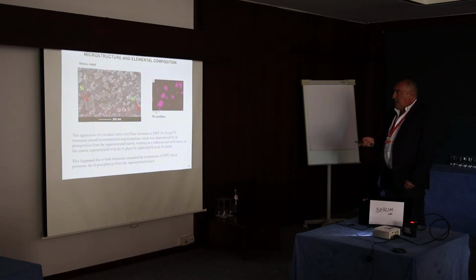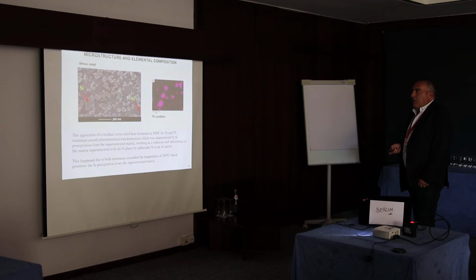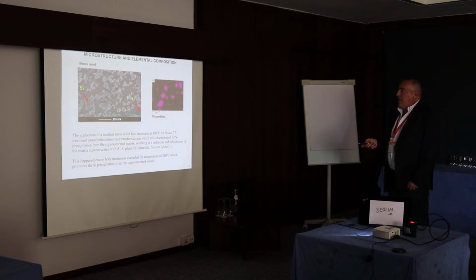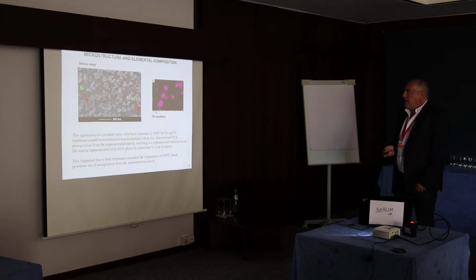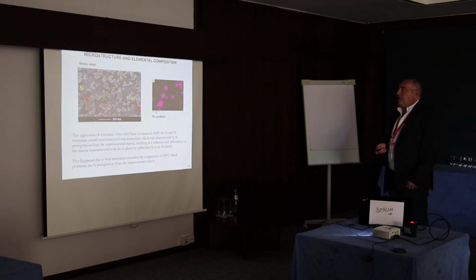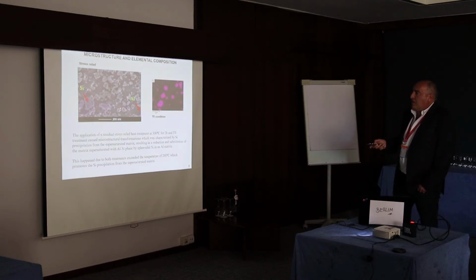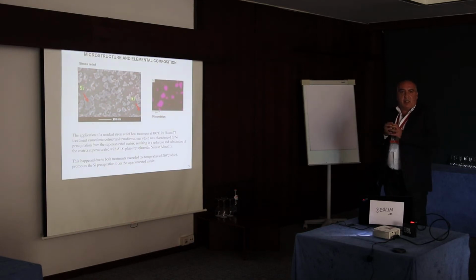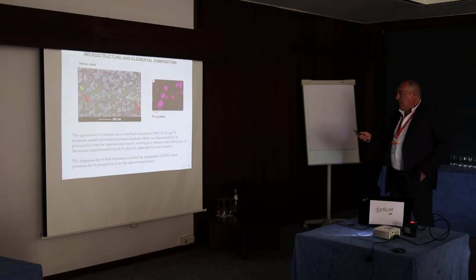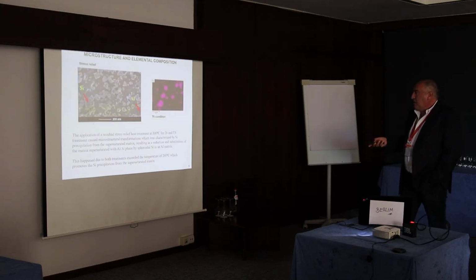This left figure presents the microstructure after the stress relief heat treatment, and this one is the EDX analysis for the T6 condition. The application of a residual stress relief heat treatment and T6 cause microstructural transformations, characterized by silicon precipitation from the supersaturated matrix, resulting in a reduction and substitution of the supersaturated aluminium and silicon matrix phase by spheroidal silicon in the aluminium matrix. You can see these spheroidal silicon particles here and the matrix of aluminium. So we don't have fine particles, but the silicon is aggregated, and then we have the aluminium part. The same happens here for the T6.